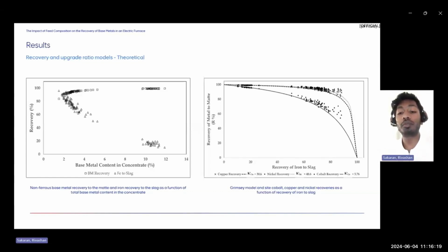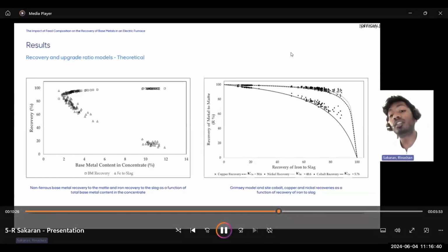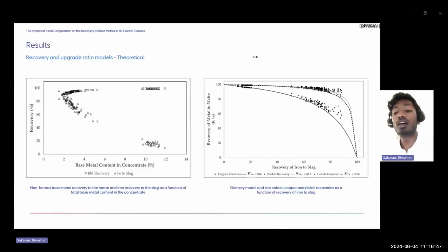low iron concentrations, for example, between 0 and 60% of iron reporting to the slag, meaning lesser iron is oxidized, the trend is followed quite well according to the theoretical Grimsey model. However, when greater iron is reporting to the slag, where that means that more and more of the iron sulfides are oxidized, we start to see a deviation from the predicted theoretical model. What's interesting is that the deviation is that the recoveries are actually higher than the inherent theoretical model as provided by Grimsey.